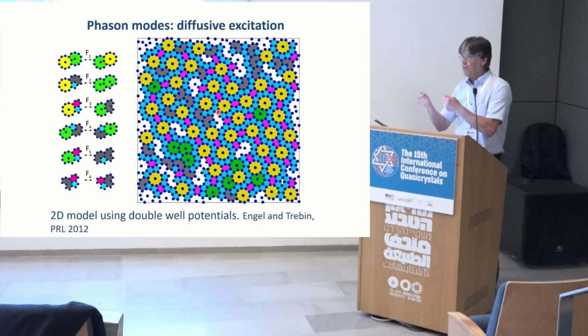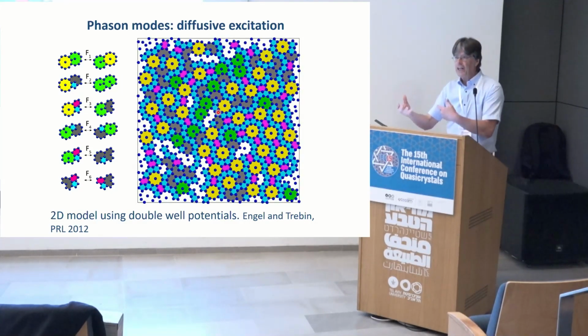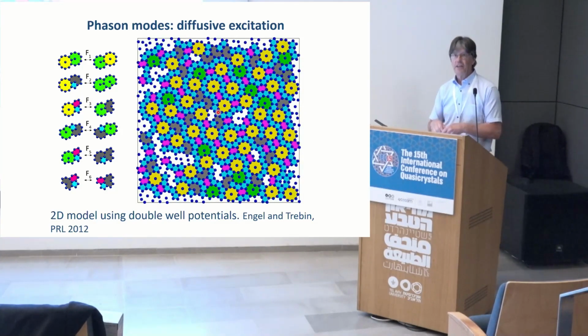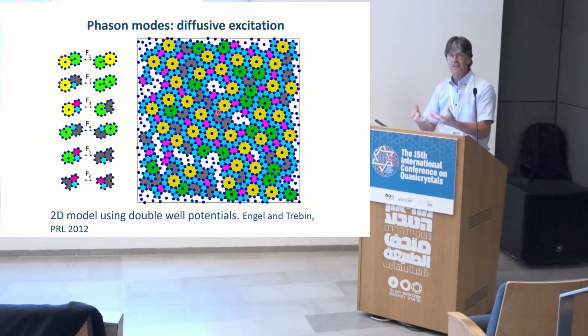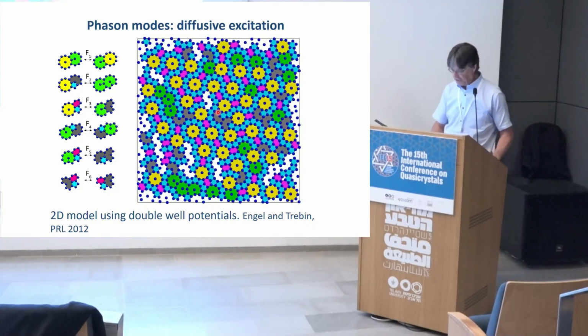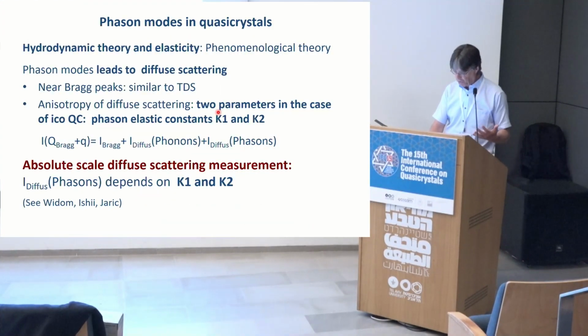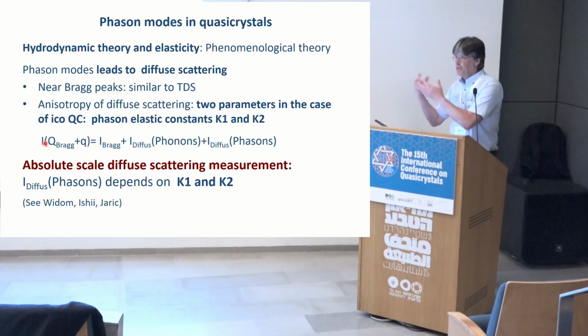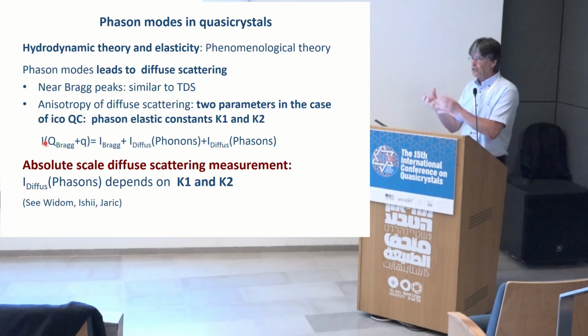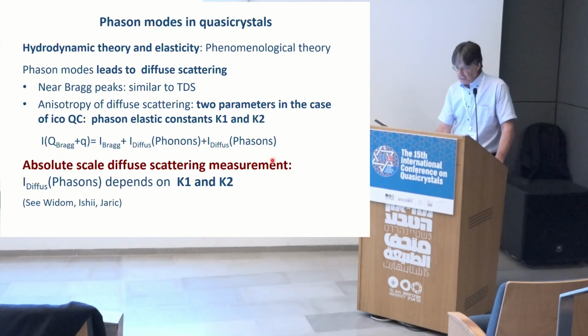And these many, many reorientations have some correlation. They are not completely uncorrelated. And it's this correlation between these reorientations that gives rise to the phason modes. And the phason modes have a very specific signature. They can be seen as some kind of disorder. We've seen in the introduction that disorder gives rise to diffuse scattering. It's exactly the same here. If we have phason disorder, we should have diffuse scattering related by two constants that we call phason elastic constants.